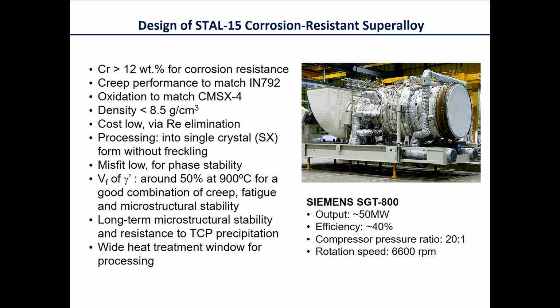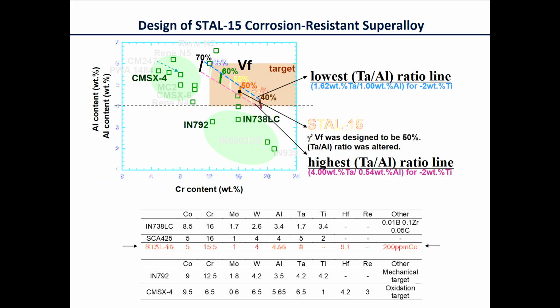And so we had an idea here of trying to invent a new type of material that would have superior corrosion resistance. The idea actually was to try to come up with a kind of stainless steel version of the superalloys. And the idea here was to have a chromium content equivalent to that of a stainless steel, greater than about maybe 12% by weight, so that we would have some very good corrosion resistance.